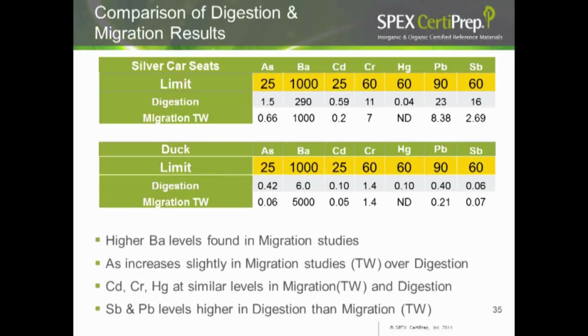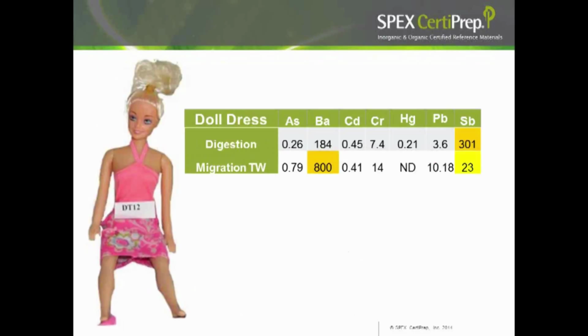It seemed that the higher barium levels were found in our migration studies. But things like the arsenic were only slightly higher in our migration studies over the digestion, and things like cadmium, chromium, and mercury were at very similar levels, no matter whether it was a migration or a digestion study. The antimony and lead levels, though, were clearly higher in the digestion rather than in the migration. Here's our doll's dress, where we can see that antimony, which was a little high in the migration but was very high in the digestion. And in our migration study, the barium would exceed the limit, but the digestion was definitely under the limit.